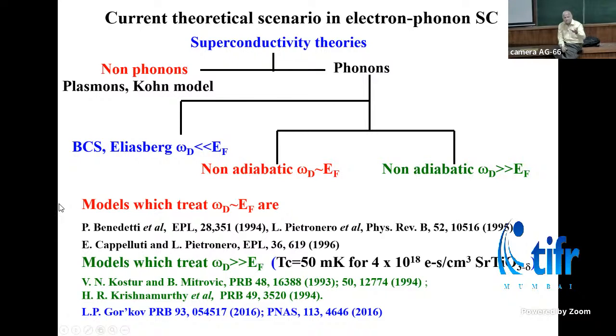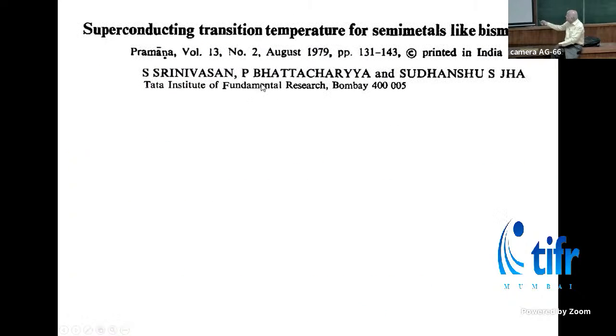There what happens is even worse. The Debye energy there is more than the Fermi energy. So there are models with Gorkov and others, everybody is going by hand. The situation there is not understood yet. So these are the two systems, with a carrier concentration slightly more than bismuth. Actually, even at 10 to the power 17 electrons, they show superconductivity. Very tiny Fermi surface, something similar to this. So there is bismuth and there is strontium titanate.